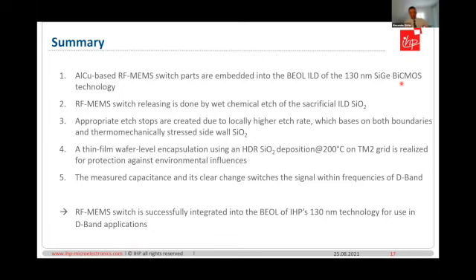Of course, if you have a standard process, we are famous for high performance transistors in BiCMOS technology, SiGe especially, and so every change is critical. So there's a weakness of my work, of course. First, we can successfully integrate these switches, but up to now this is not qualified. Every flow has to be qualified to offer this to the customers. In this case, at least the silicon rich nitride as stop layer is integrated, and this is not qualified at the moment.